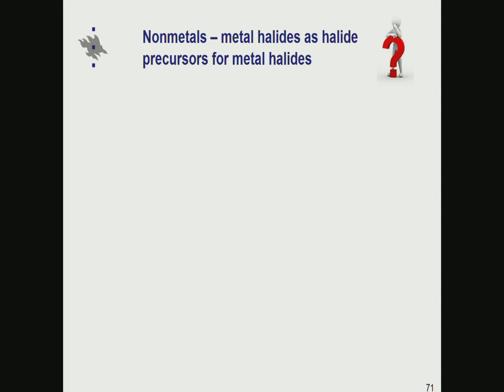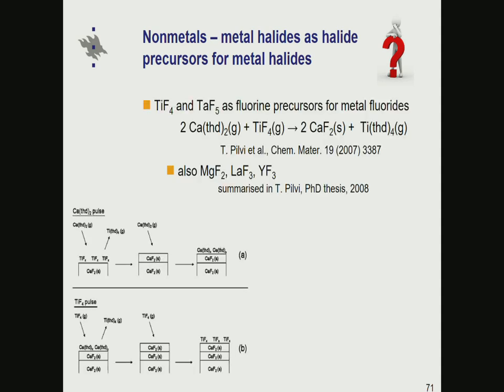Then, this is a little bit of an odd statement, that's why I add this with the question mark. We have also studied a chemistry where we use metal halides as halide precursors for metal halides. What that means essentially is that we choose one metal halide which is volatile, and then we use that for depositing a metal halide which is definitely not volatile. There is an exchange reaction, where calcium, in this case a beta-diketonate compound, is alternately pulsed together with titanium tetrafluoride.